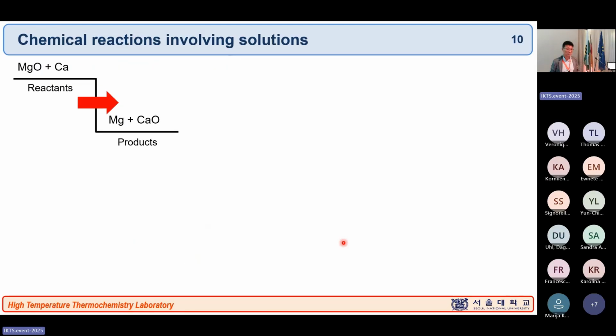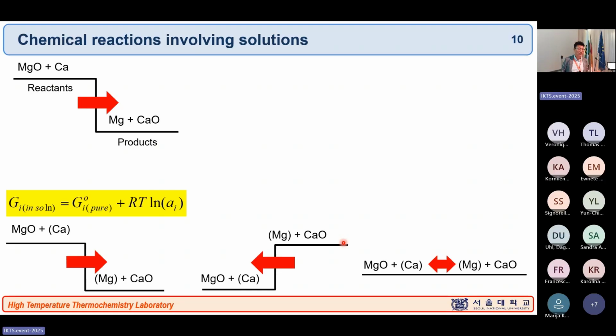So let's go back to this example again. If you are talking about the pure standard state, CaO is always more stable than MgO. So the Gibbs energy change for the reactant and product is more stable. Okay? But now, if I allow this calcium and magnesium to make a solution phase, now we can change the Gibbs energy of reactant and product actively, simultaneously.